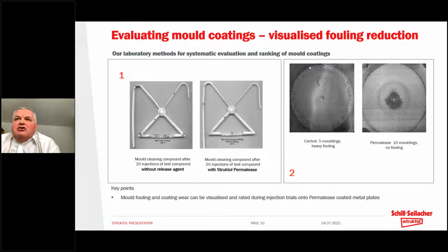But by contrast, with the control compound, we can see a buildup of black spots at the edge of the mold flow, where mold fouling is starting to build up right at the end of the degree of mold filling that we calculated. Of course, no sign of wear in the center because we had no coating, but the absence of the coating also promotes a very early buildup of mold fouling. So that mold would require cleaning far earlier than the coated mold.